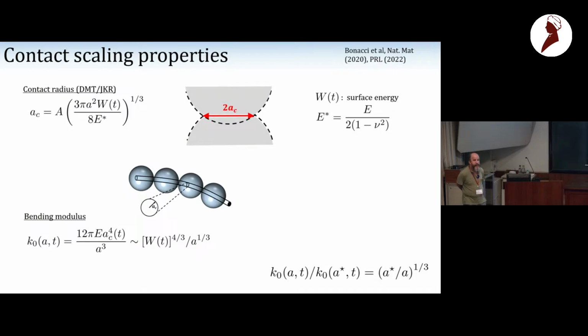Yeah, I didn't understand qualitatively where the bending modulus comes from. So, well, the particles are adhesive, and the point is that the edge of the contact is pinned. And so then it resists rolling. Because you have a pinning of the edge, this is fixed. So it's pinned. It's not the same as solid friction, right? Solid friction is not the same. No, it's not exactly the same. And actually, it's a pinning problem, and the opening is in fact related to fracture, and it will come. Yeah.